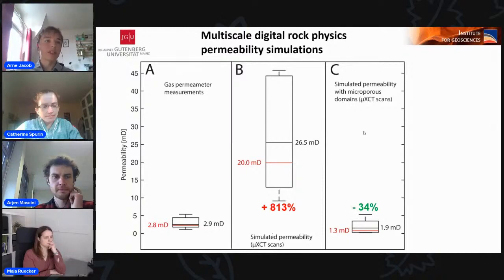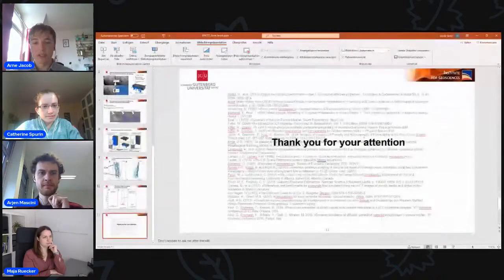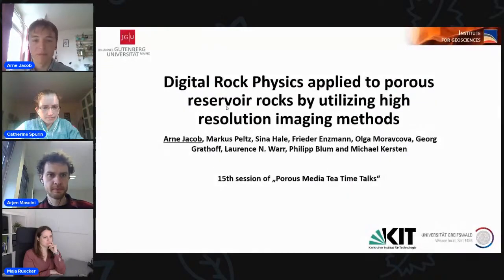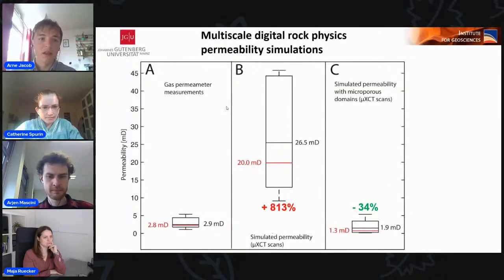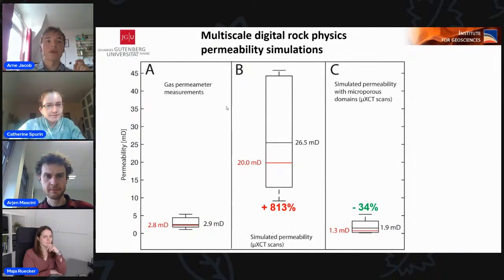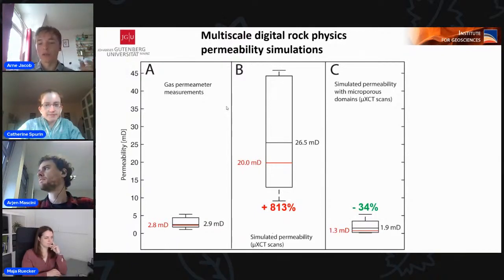When we simulate the permeability only on the original images, sorry, that was my fault. We would be 800% above the permeability which was determined by gas permeation flux experiments. When we include the information we have from FIB-SEM imaging, we are very close to the true permeability values, which are coming from experimental measurements. So around 1 to 5 millidarcies. Yes, with this, I want to close my talk, and I want to thank you for your attention.